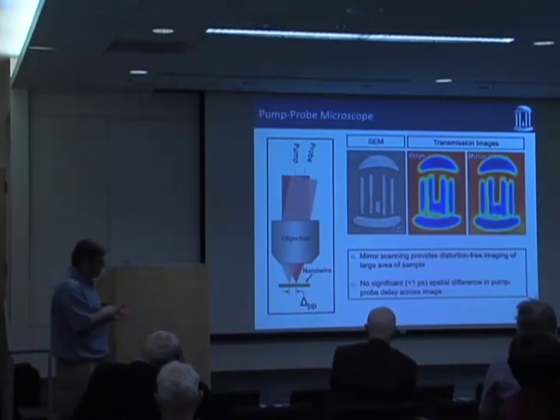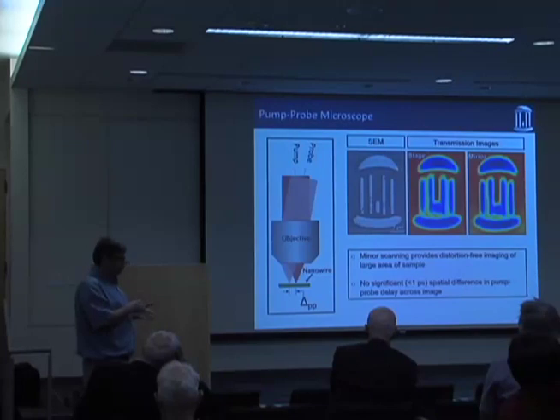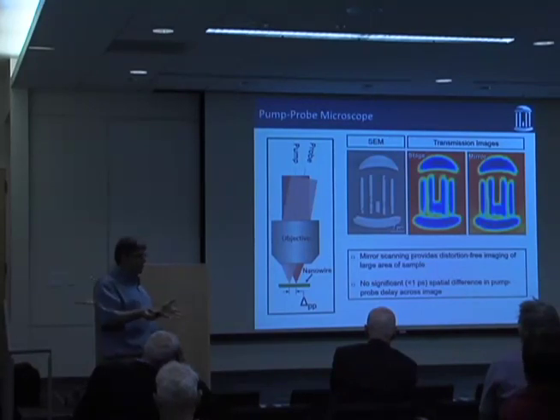If you've done ultrafast spectroscopy, you know that as soon as you introduce path length into your beam, you're going to introduce delay. But it turns out that in this particular case, geometry is on your side, because whatever path length you introduce by tuning one mirror is taken up by the other. So, as near as we can tell, there's essentially no time delay difference across the image.